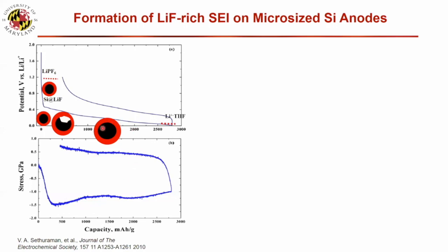And because at here, the solvent is not reduced, the polymer is not formed, the only thing formed is lithium fluoride. Only at the very end, when the potential reaches the lower lithium THF reduction potential, then they can start. But normally we already formed a lithium fluoride, so theoretically it's a 0.3 reduction potential. But if we have a lithium fluoride there, there should be an overpotential. This is only formed at the end of lithiation.